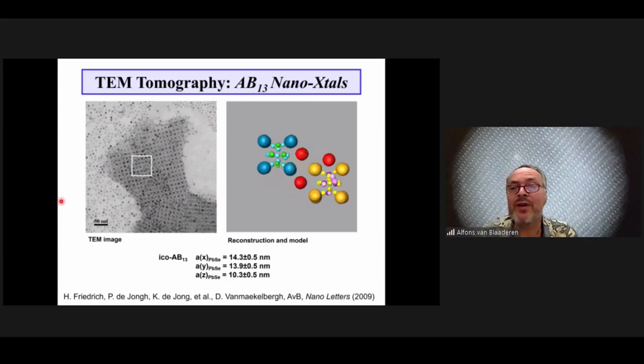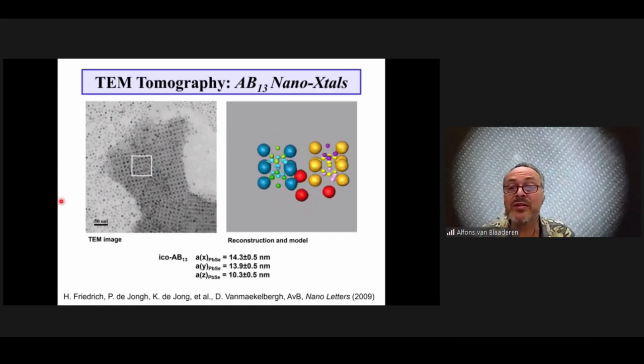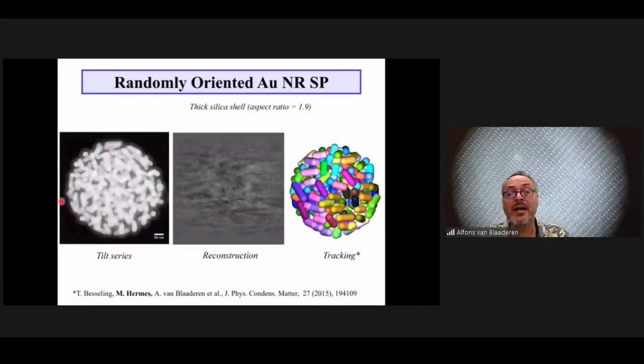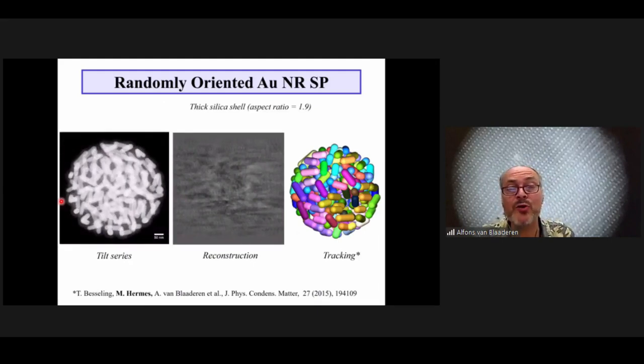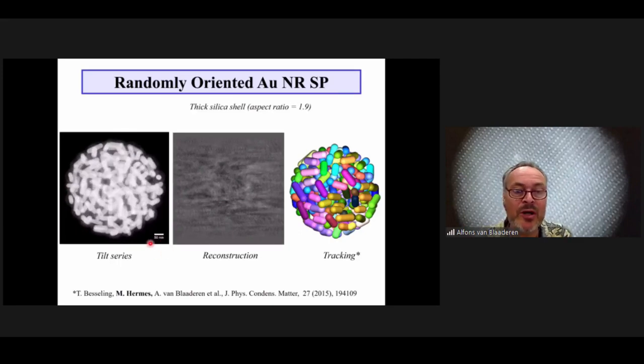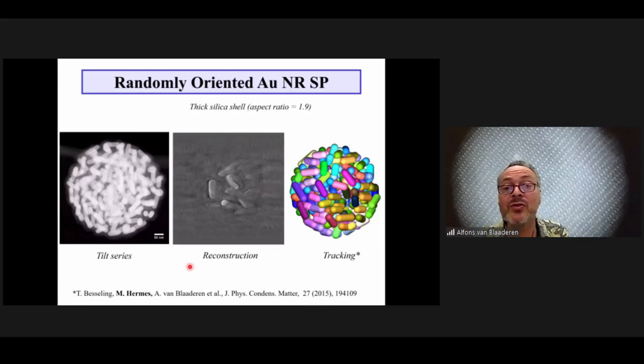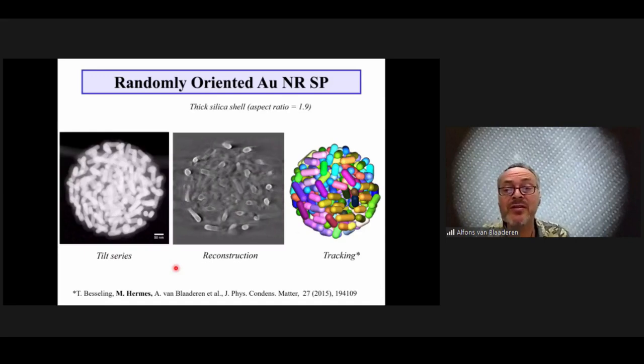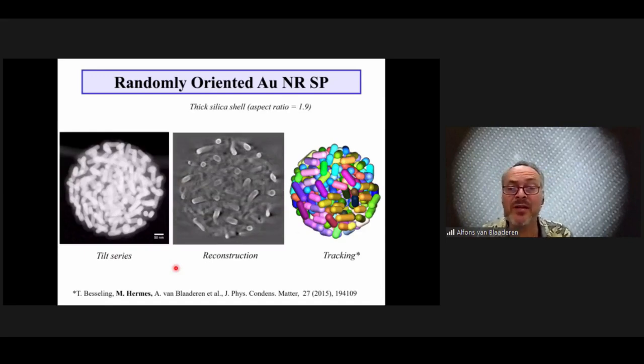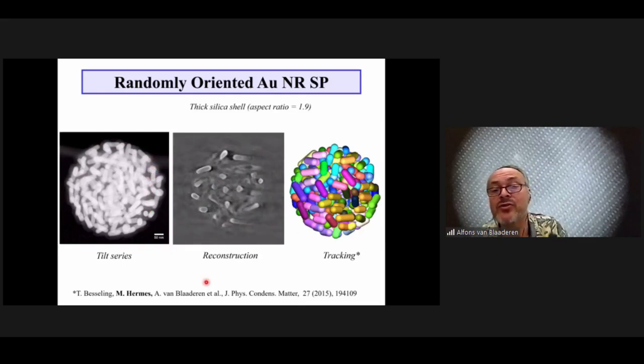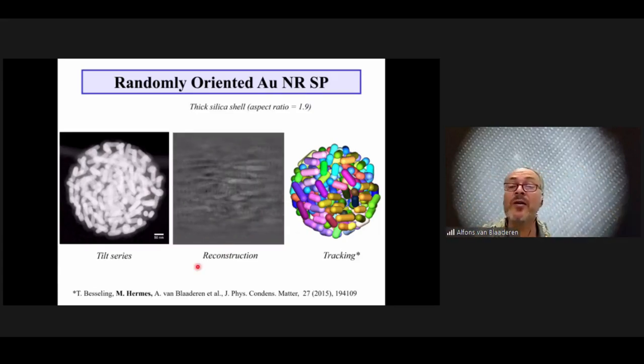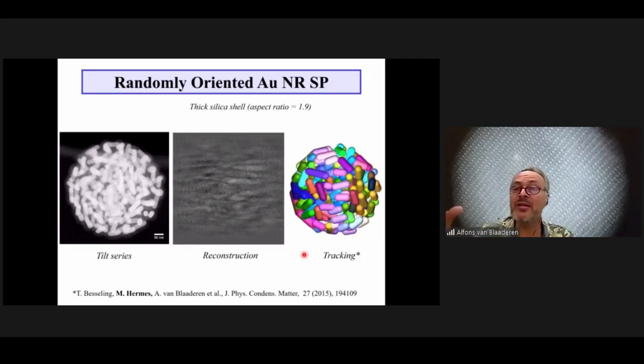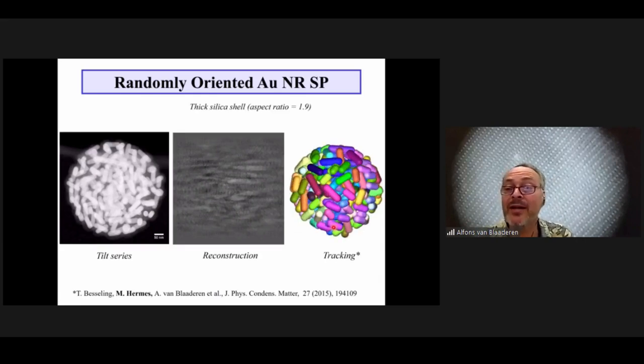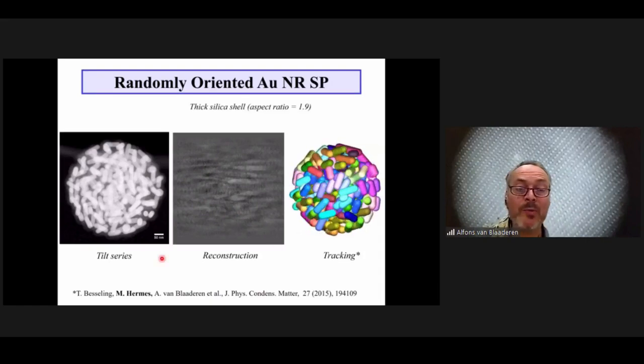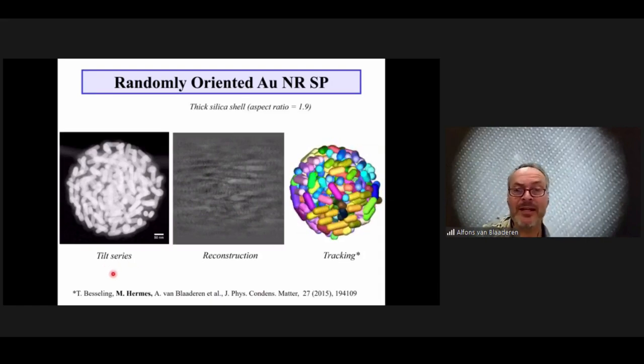This was just a crystal with 5 or 6 layers, but I'll show you results of crystals which have layer thicknesses on the order of 30 particles. So this is another example of a superparticle formed with gold nanorods, and notice here that the scale bar is 50 nanometers. These particles did not have an aspect ratio large enough to form liquid crystals, but they're nevertheless important for plasmonic properties. So you only see the gold nanorods by the contrast. I should mention there is a mesoporous silica layer which gives them a thicker extension, and in the tracking this silica layer is not shown, but you can see that in 3 dimensions we get all the orientations of the particles, and because this was a relatively polydisperse sample, even the different sizes, all from the analysis of the 3D data sets.